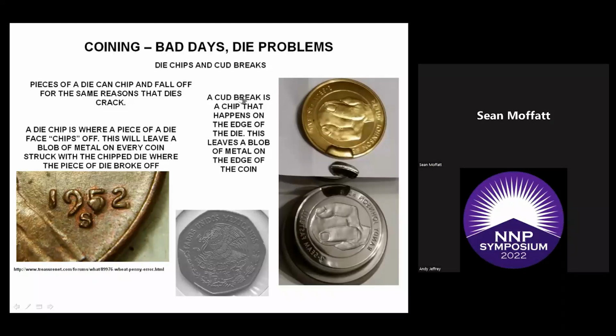Now, a cud break is a chunk of the die that just happens to break off on the edge of the die. This leaves a blob of metal on the edge of the coin. So you can see right here, there's a big old blob of metal on the side of this token right here. And here's the die right here, and that's the chunk of the die that broke off when that happened. And over here, I have a nice Mexican 10 peso coin, and you see just a big old chunk of that die broke off the edge. So those are known as cud breaks.